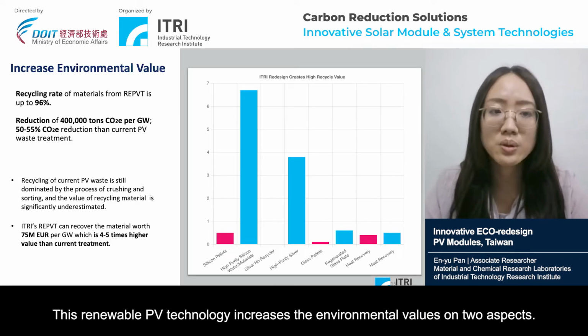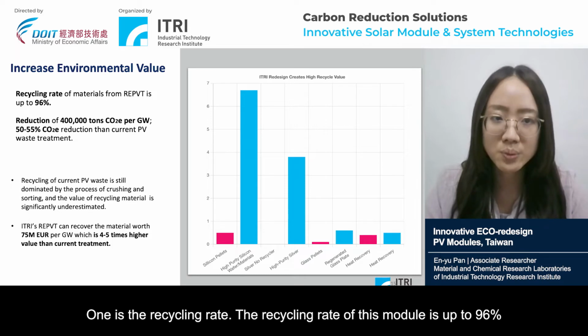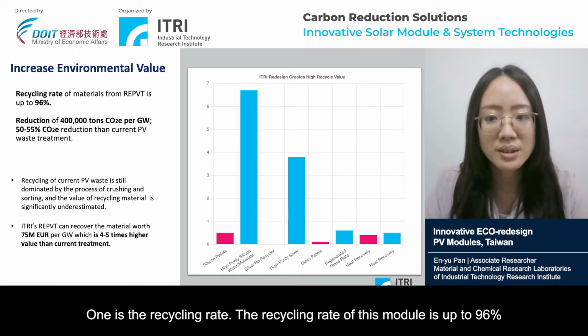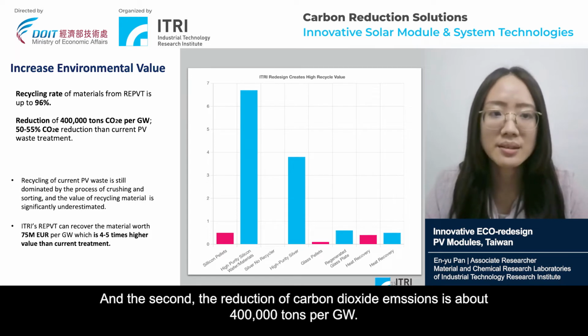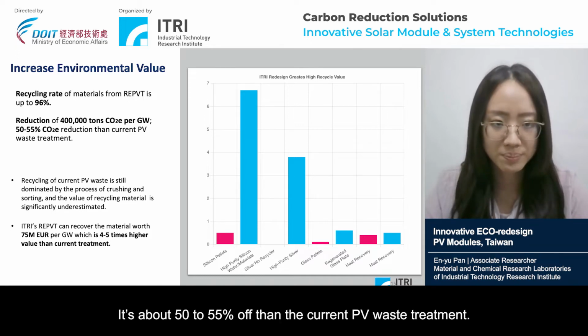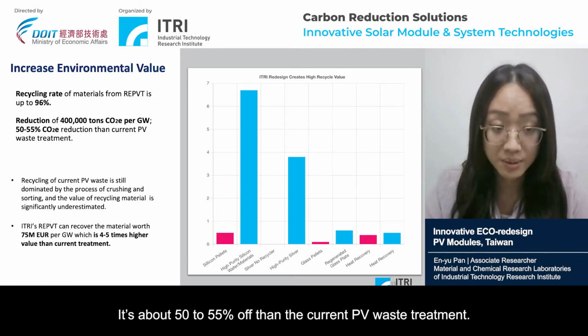And this renewable PV technology increases the environmental value in two aspects. One is the recycling rate. The recycling rate of these modules is up to 96%. And the second, the reduction of carbon dioxide emissions is about 400,000 tons per gigawatt. So it's about 50 to 55% lower than the current PV waste treatments.